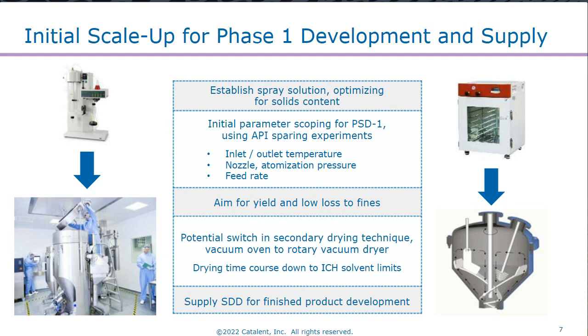So we'll be going from initially lab scale spray drying, so for instance using the small scale spray dryer on the top left, and at that stage we'll be working mainly to optimize the spray solution for solids content and to confirm the composition of the solid dispersion. As we move to larger scale spray drying, so bottom left we have our PSD1 spray dryer that we have in Nottingham, and we have approaches that are API sparing to establish the manufacturing process on the PSD1.